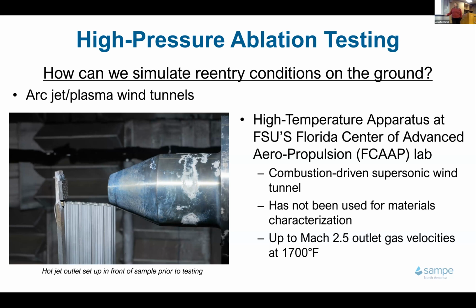So we're looking at these reentry conditions. This specific one is a hot jet, combustion driven supersonic wind tunnel. There's an ethylene based burner, up to Mach 2.5, outlet gas velocity at 1700 degrees F. So we're going at 1700 degrees F at Mach 2.5, and here's our core little sample in the jet exhaust. This setup has previously not been used for materials characterization.